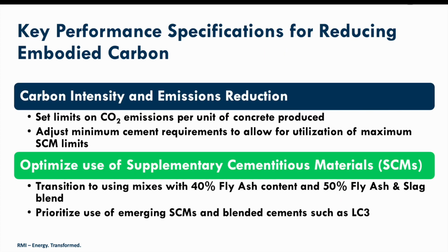What's next? DOTs should look at setting carbon intensity and emissions reduction targets. Set limits on carbon dioxide emissions per unit of concrete produced. Adjust minimum cement requirements to allow for the full utilization of maximum SCM limits. Further, the use of SCMs should be optimized by transitioning to mixes with a 40% fly ash content and a 50% fly ash and slag blend. Prioritize the use of emerging SCMs and blended cements such as LC3. And with that, I'll hand you over to Professor Hooton for his section of today's presentation.